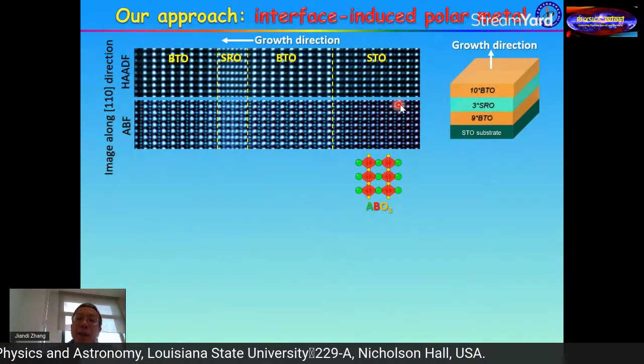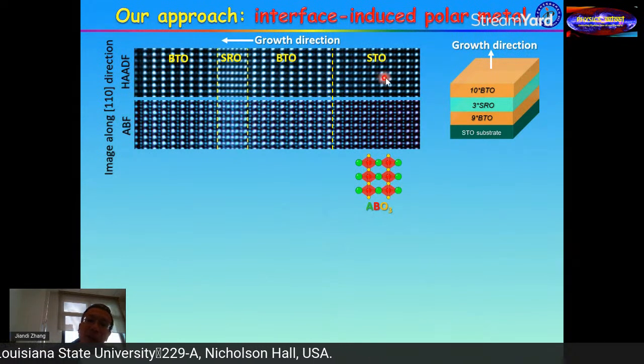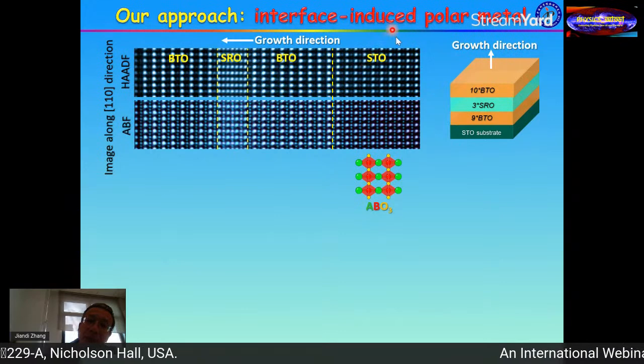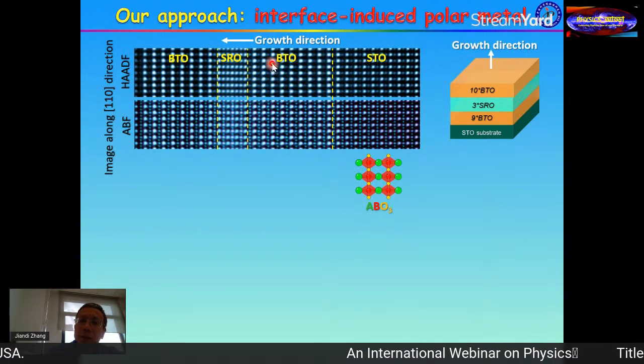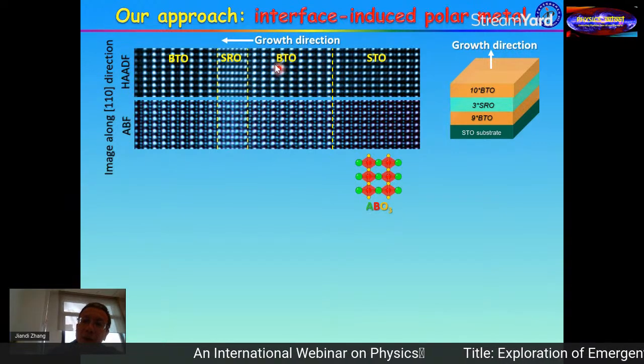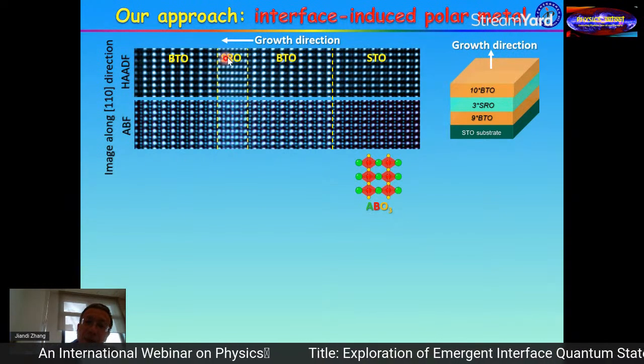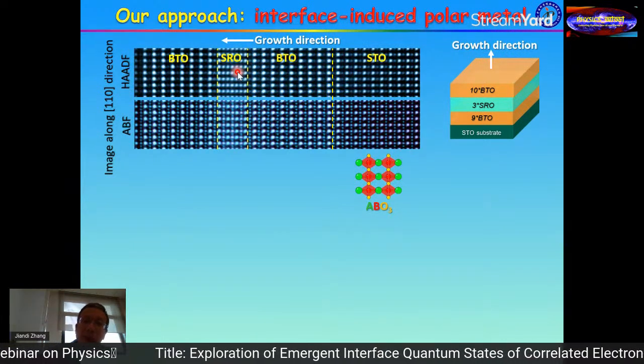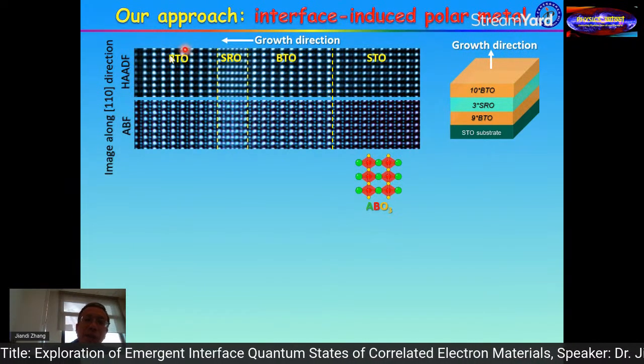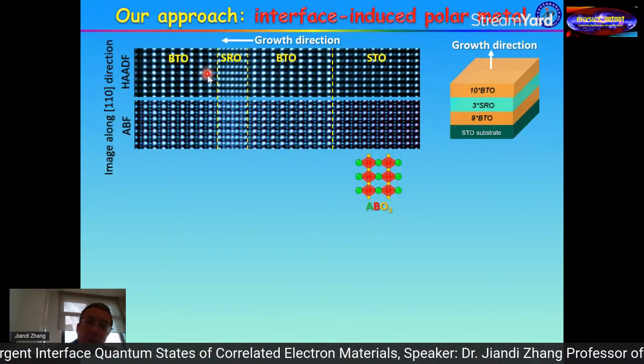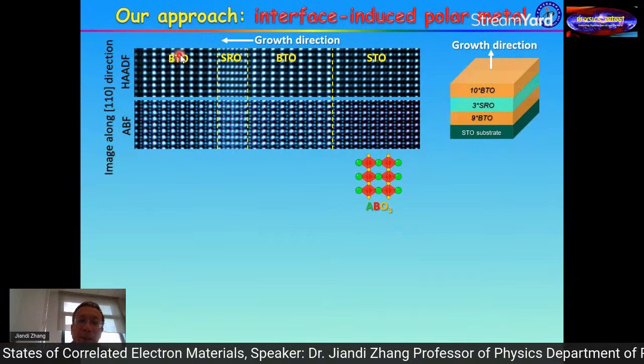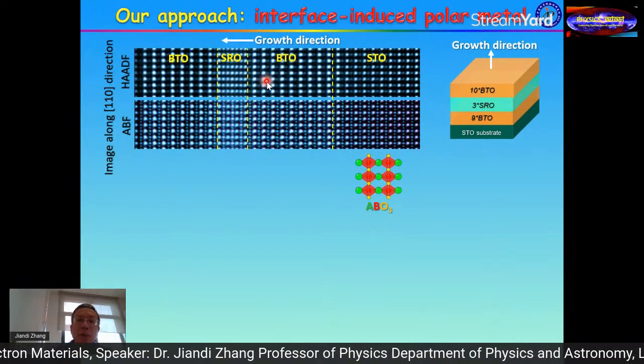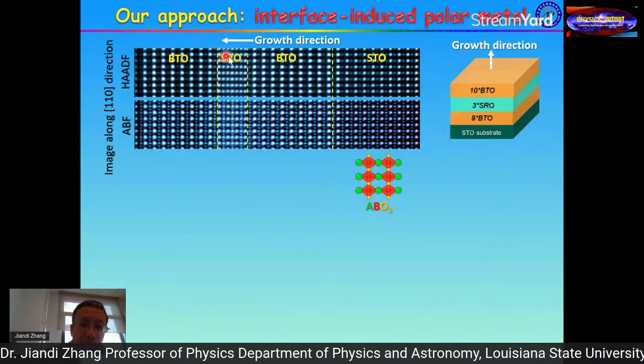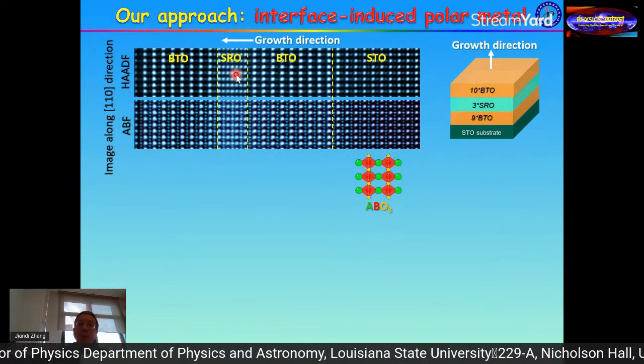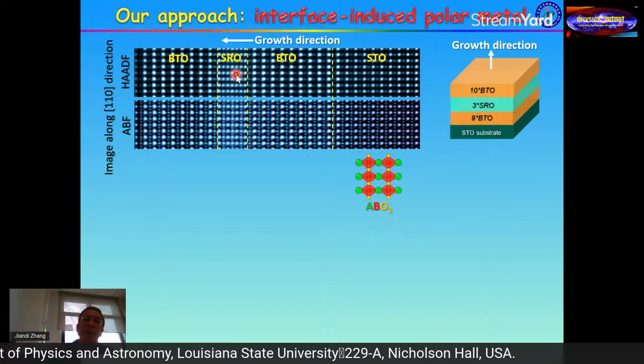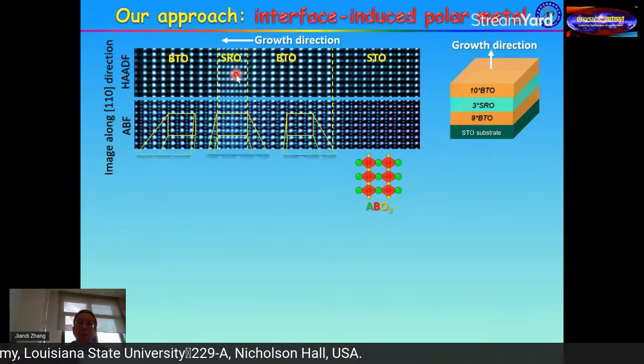All right. So what do we do? We grow this material, and now it's grown this way. Okay, let's look at this way. So this is my substrate, using strontium titanate, and I grow 9 unit cells of the barium titanate, and then I grow 3 unit cells of the strontium ruthenate, and then I grow another 10 or 9 layers of the barium titanate. And the purpose is I use the barium titanate to create a polar structure, to try to influence the strontium ruthenate. And at the same time, I want to maintain the strontium ruthenate property. And this is what we are doing.